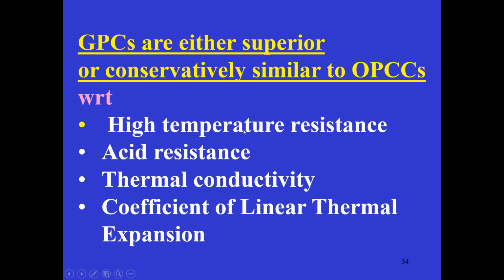And for temperature resistance, if it is made properly, we can get even temperatures of 800 degrees centigrade. Okay, and definitely not every geopolymer concrete is ideal for resistance. It depends upon the formulation. Whereas Portland cement simply goes away at 300 degrees centigrade. It cannot take much load, and deterioration of strength occurs after 300. By 500 to 600, its strength is almost gone. Whereas in geopolymer concrete, with proper formulation, we have got results up to 800 and above for some formulations.